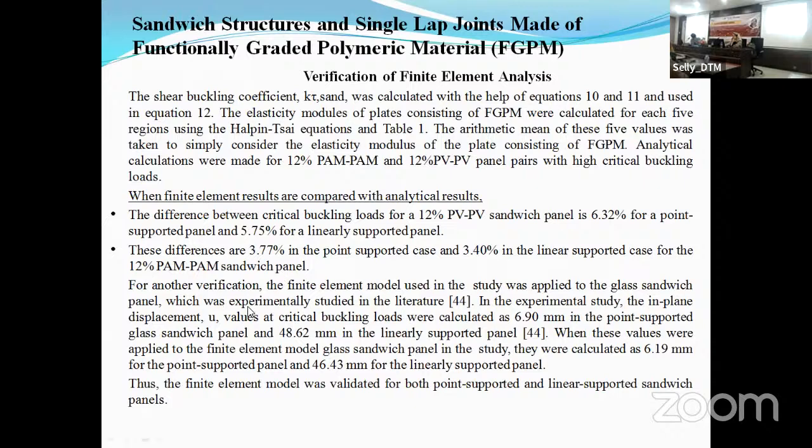so the glass was experimentally studied. They used the linear support, they used the point support in architecture. So it's used from the literature. And then its experimental study calculated 6.9 millimeter in the point support sandwich panel and 48.62 millimeter in the linear support panel.